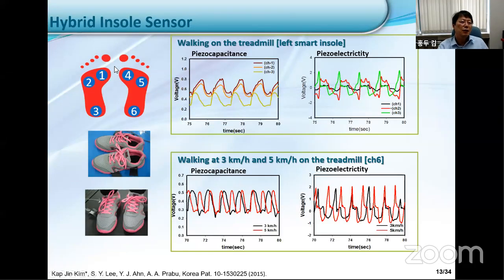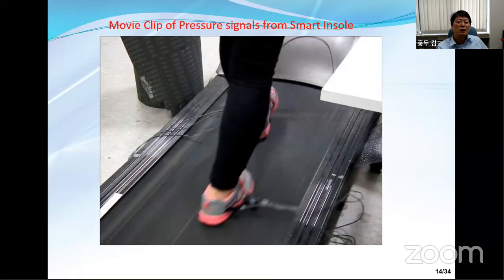From these materials, we made a hybrid sensor quite a long time ago. As you see here, we made three different types. In the piezocapacitance, we can see some difference between the 3 to 1, and as you see here, the person has a very good walking behavior. But with the piezoelectricity, the signal behavior is much quicker, and we can get a similar result. And of course, when we run, the signal becomes faster and faster, as you see here. So this is one of the examples.